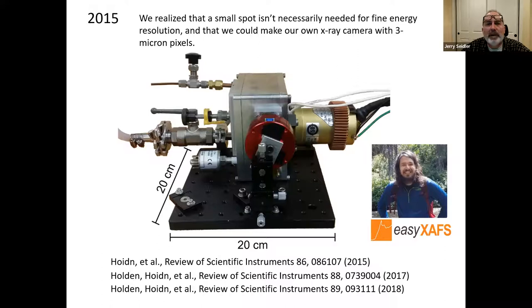And so we realized, sort of rediscovered something that had at least been partially known in the community previously, that a small spot size isn't necessarily needed for fine energy resolution. And also in an independent project in plasma physics, we had already been developing our own X-ray cameras for low energies with about 3 micron pixels. And so Will Holden, now with easyXAFS, put that together into this adorable little instrument. And you can see the size of the breadboard is really quite small.